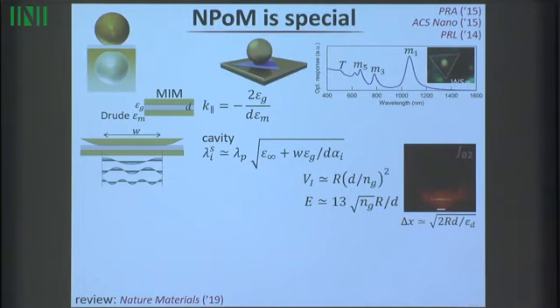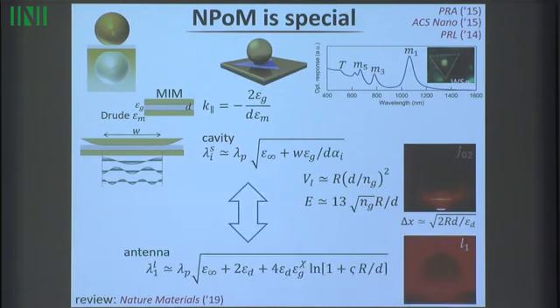Some years ago we didn't believe things like this were possible, and now these are completely routine. The mode looks something like that. So I have a very strong and intense mode for light that I can couple to. This nanoparticle on the top acts a bit like an antenna. There's another mode in the system which is more distributed, and free space light can couple to this mode here, which couples to this mode here, so it puts light very efficiently into that gap. Otherwise we couldn't really see what was going on in this system. So we've been using these modes for a bit of time.